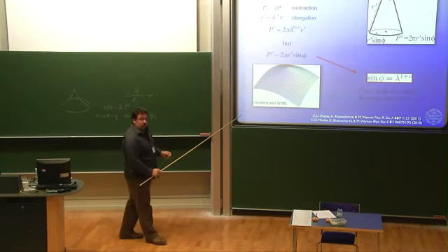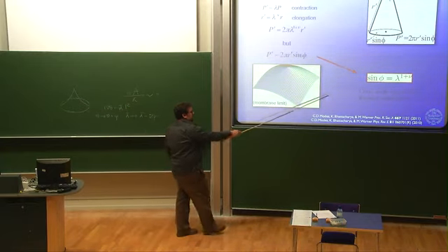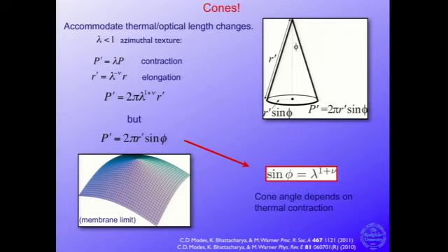Interestingly, in the limit of low strains, that spherical cap becomes large, and you get a metastable region where the whole sample prefers to pay the strain cost of staying flat, and then it pops up. And this has been seen recently in simulation by Robin Selinger and her group, which is interesting and nice.